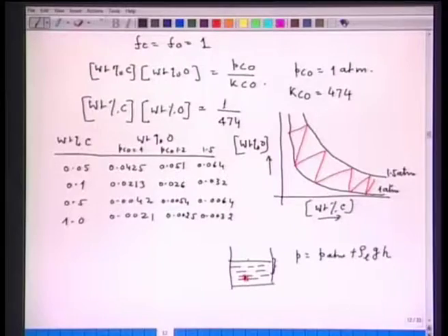Now, in another situation, for example, if the nucleating site is somewhere here, at the slag metal interface, then we can consider the nucleating bubble will be experiencing only atmospheric pressure, for example, equal to 1 atmosphere. So, between this range where the CO bubble is nucleating, depending on that, the dissolved oxygen in steel may vary.